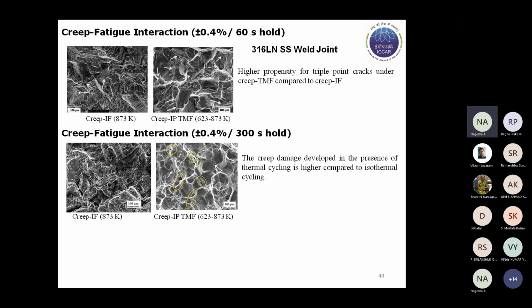This is similar to the earlier results. The normal isothermal creep fatigue. This gives the difference in the fracture morphology between the isothermal and the in-phase creep TMF. Similar to what was noticed in the continuous cyclic tests, creep IP TMF gave rise to significantly more creep damage, reflected in the form of creep cavitation and triple point cracking on the fracture surface.